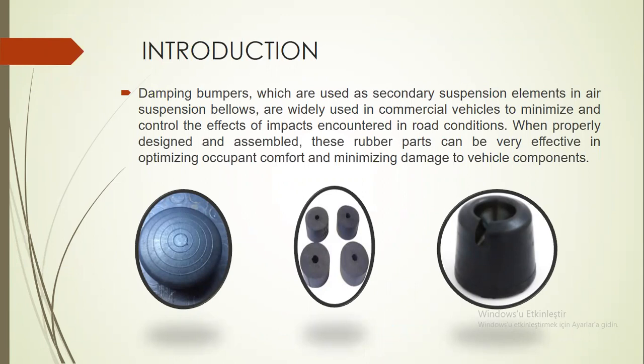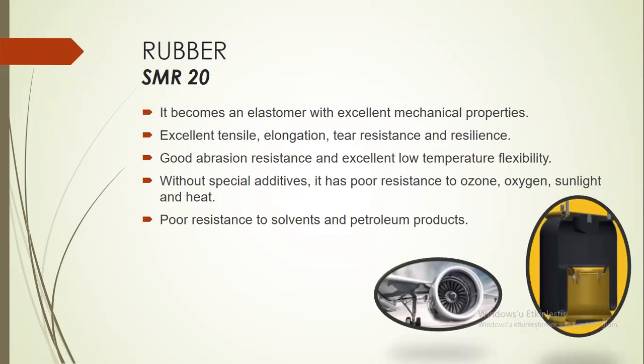This study presents the experimental investigation results of cyclic compression at 1, 2, 3 millimeters per second speeds of the hysteresis behavior of damping bumpers prepared with two different filler materials, carbon black and multiwall carbon nanotube, under static loading. We used rubber SMR 20.